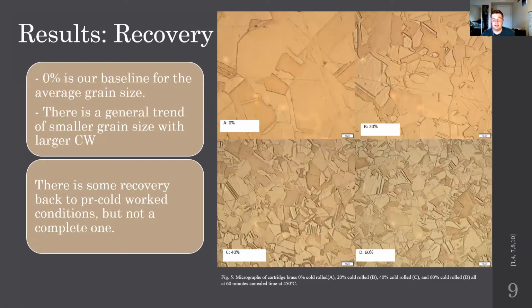We were also interested in seeing how much these grains had recovered back to our original samples. So in A, you have our uncold worked sample that is just completely annealed, and that's our baseline for how much these grains can recover back to their original position. And you can see with increased degrees of cold work, 20%, 40% to 60%, there's a general trend that with each increased cold reduction, the grain sizes are ultimately smaller. So all of these are at 60 minutes, 1 hour, our maximum annealing time, just to see at these longer times, how far the recrystallization process can get. And so you can see that none of these actually achieve the same grain sizes as our original brass sample. And so this tells us that the recrystallization process, or the grain growth process, is not necessarily complete. So there's some recovery, but not a complete one.